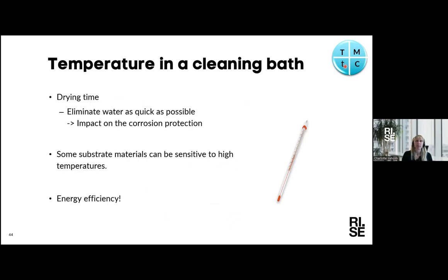Temperature we already mentioned. It's one of the 4 parameters. So it influences, of course, the drying time. If you have a higher temperature, the water will leave faster, and how long the water stays on the surface has an impact on the corrosion, of course. And also, but there's a limit, of course, both in energy efficiency, but also for the material that is washed, how high temperature you can use in your washing system, or in your cleaning process.